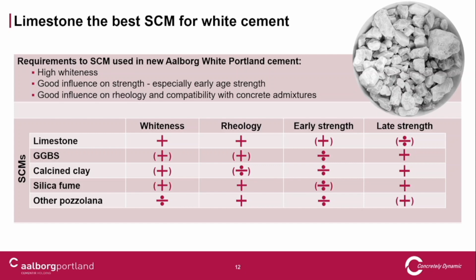On early strength, limestone has a good influence; all the others have a negative influence. On late strength, limestone isn't that good, but as we saw, our clinker has a very high late strength, so it's okay for us to have a little reduction in our 28-day strength since the supplementary material doesn't contribute much there. So limestone is a good choice for us to put into the white cement.